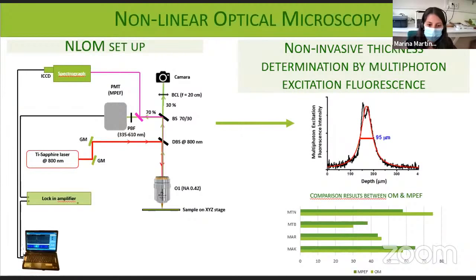These techniques allow for a three-dimensional characterization of the structure and thickness of multi-layer and multi-component substrates. In this graphic, we can see represented the thickness at the full width at half maximum, resulting from a Lorentzian function fitting. Also, we observed a good agreement between the multiphoton excitation fluorescence and the optical microscope. It should be noted that the nonlinear optical microscope was developed in our institute, and until now, this is the first time that this non-invasive method is used to study degradation layers of glass.